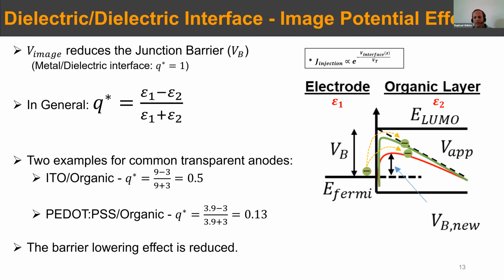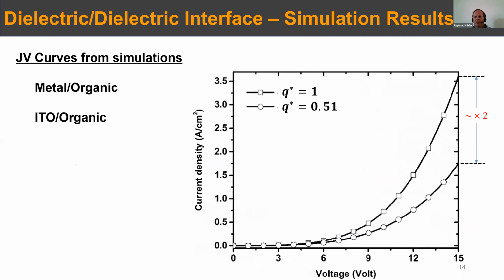So instead of having a low barrier, you will have a much higher barrier for injection. It doesn't have to be much, but depends obviously on the choosing of the material. And if you just look at what we did as a simulation, you can see that there is an expected difference of about ×2 between the current density when you have a Q star of a metal and when you have a Q star of an ITO.